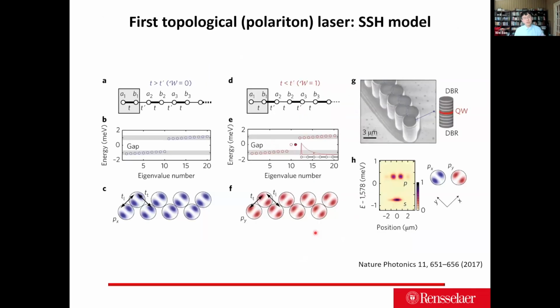Although the theory was first proposed in the two-dimensional case, the first experimental topological polariton laser was demonstrated with a simpler model called the SSH model. Essentially, if you have lattice sites and the hopping between the lattice sites is different, you will have a configuration with a trivial case where you don't have any topological band, or a non-trivial case where you have a localized topological edge state.